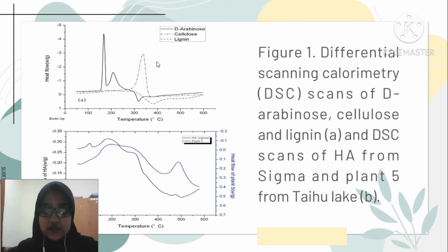For the monosaccharide DSC curves, which is the D-arabinose, there are 4 different peaks observed, which is 3 endothermic peaks at 159 to 170 Celsius, 207 to 222 Celsius, and 292 to 312 Celsius, as well as an exothermic peak at 305 to 343 Celsius.